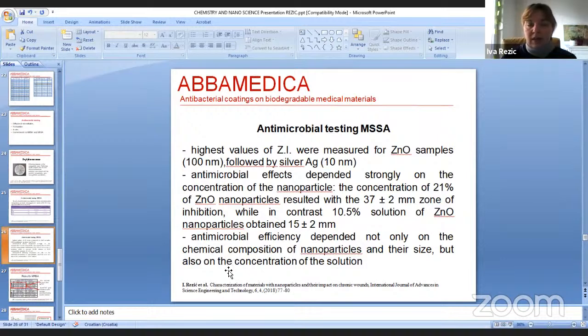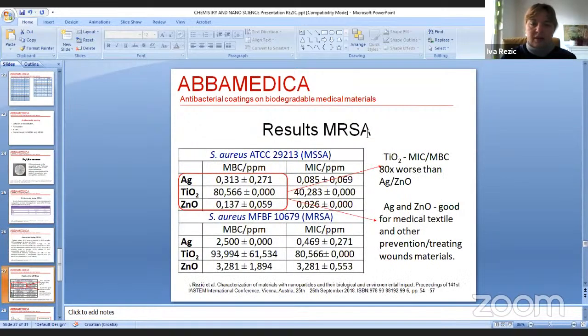And we have some really contradictory data because in our experiments, smaller nanoparticles are more efficient than bigger nanoparticles, but we still need to prove this. So for MRSA microorganisms, you saw the results of silver and zinc, and titanium oxide is 80 times worse, so it's actually not a good goal for our future application.